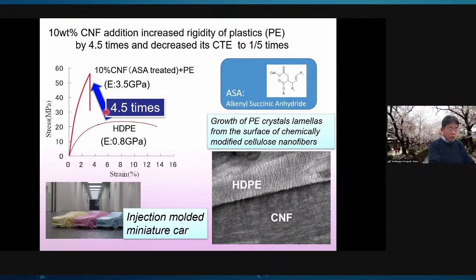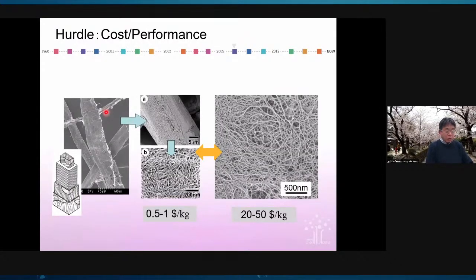However, there was a big hurdle to commercialize ASA-treated CNF reinforced PP and polyethylene. That is the production cost. Pulp is around 50 cents or $1 per kilogram. But after the disintegration of pulp to make nanofibers, the price increases to $20 to $50 per kilogram.